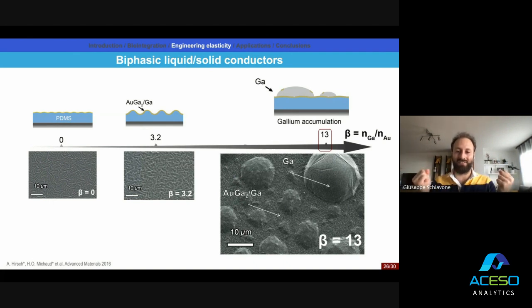When you stretch this device, the gold will crack, so you will have severed electrical connections. But the gallium on top will actually bridge these severed connections because it stays liquid, and it flows wherever you expand the device. So this was another way of introducing stretchability into soft devices.